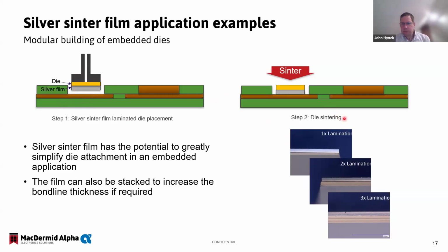Another advantage you get to the paste is, I had mentioned that the film comes in a thickness, but you can do multiple lamination steps to build up your silver sinter material layer and get a larger bond line if desired, or if it's required. Say, for example, in this application, if your stack up requires a larger bond line and larger silver sinter material area, you can do that by doing multiple laminations.